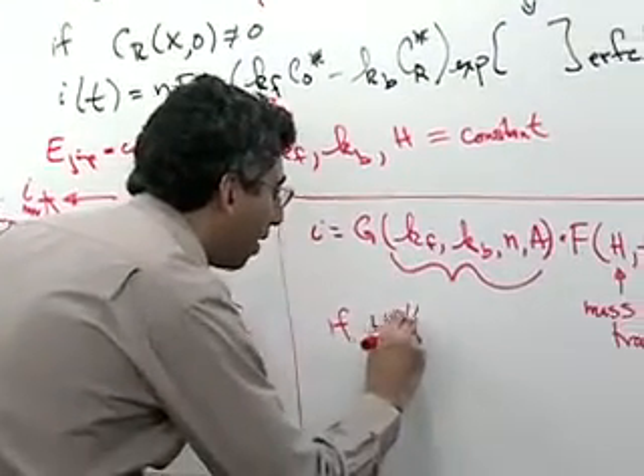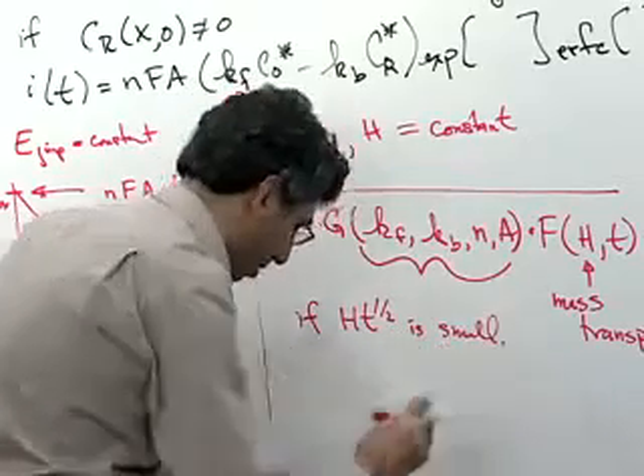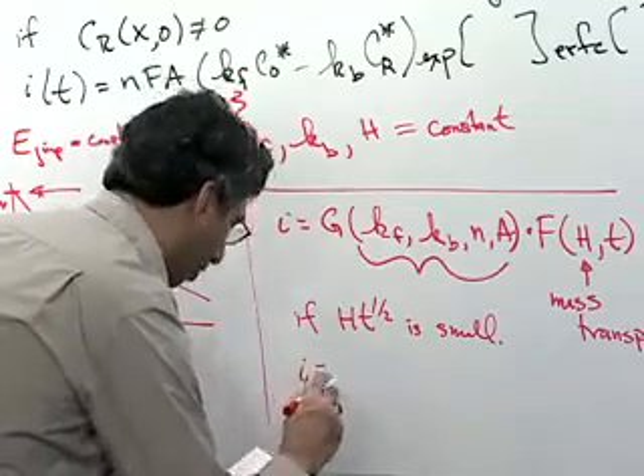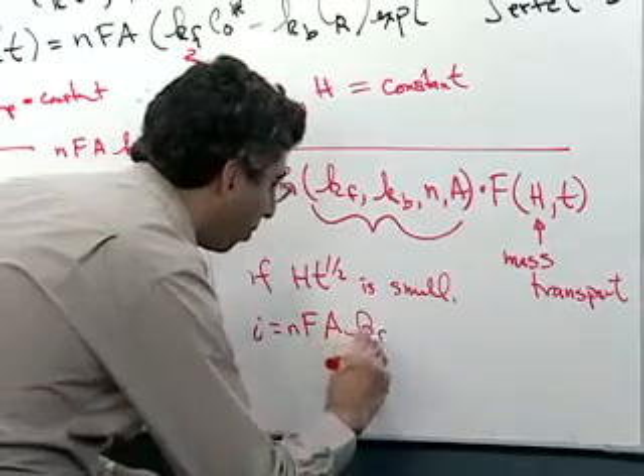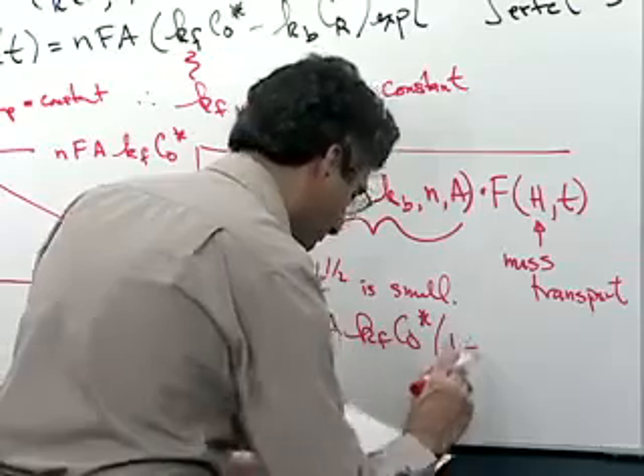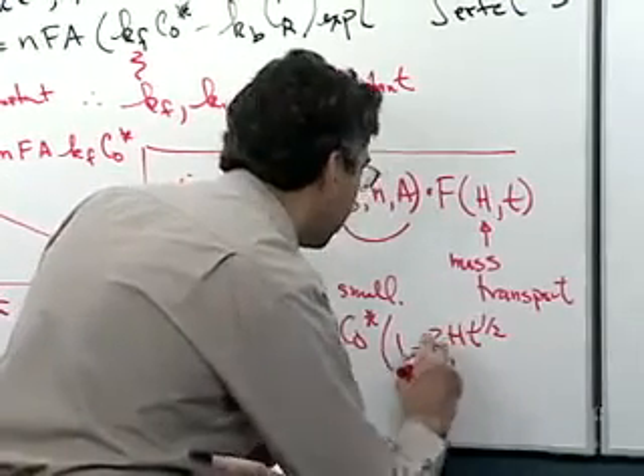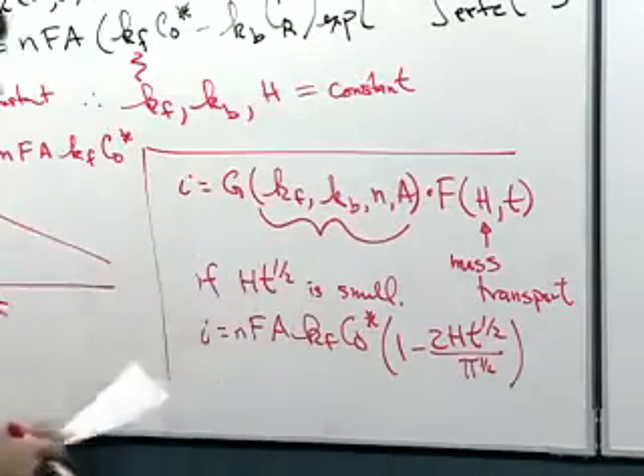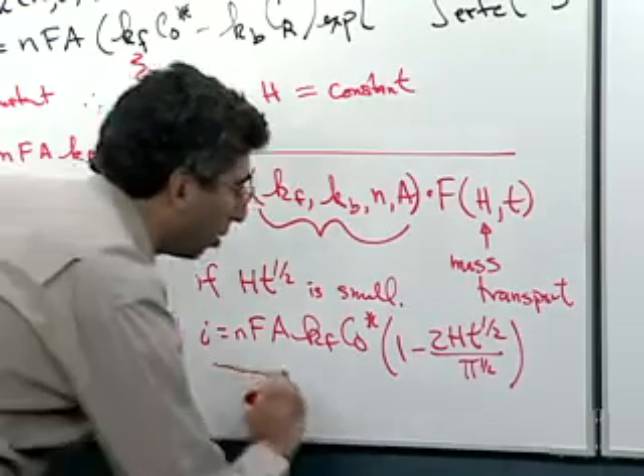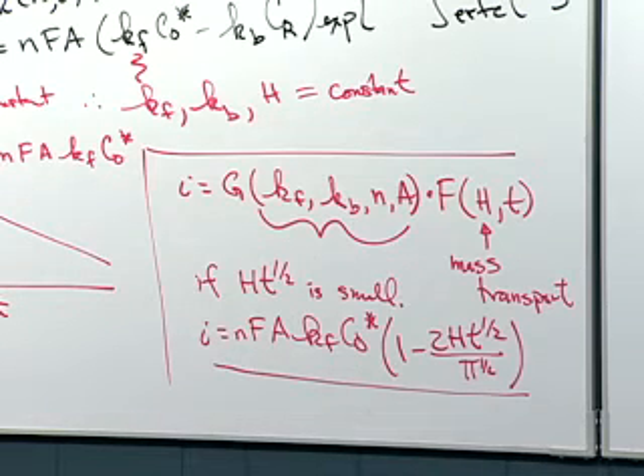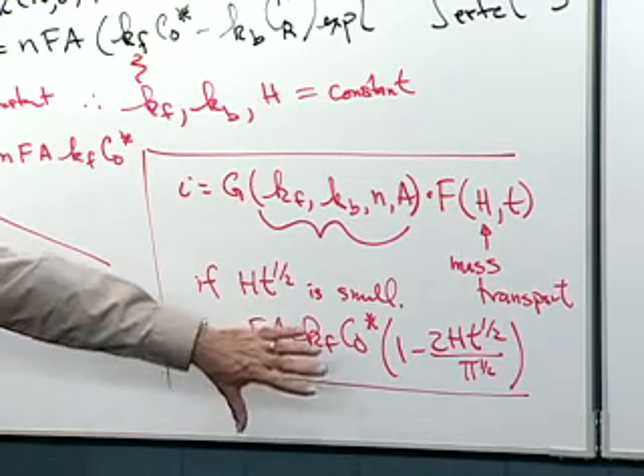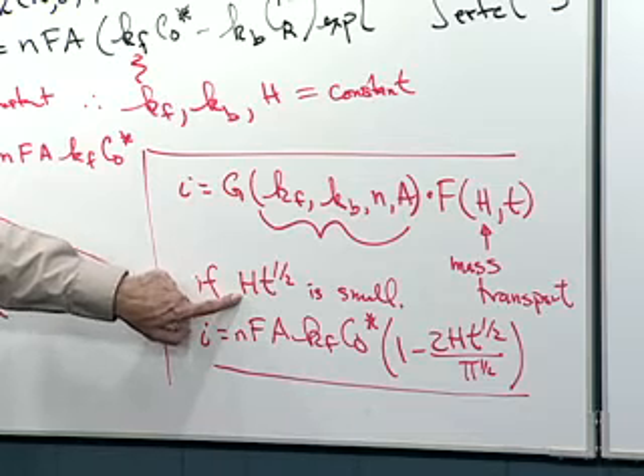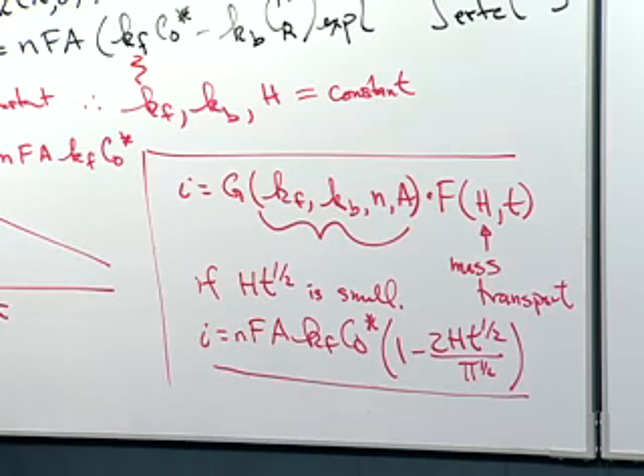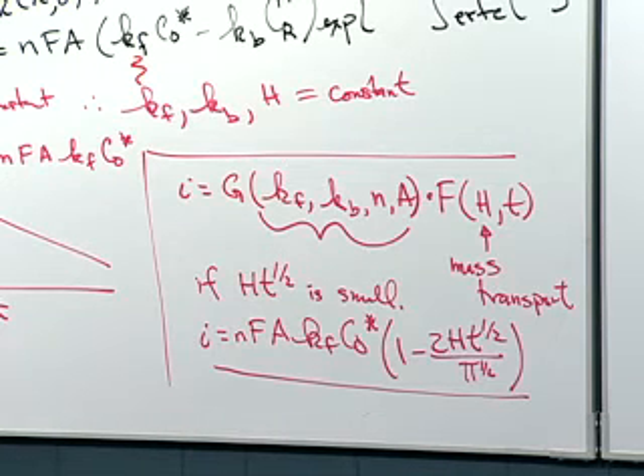And it turns out, if h times t to the 1/2 is small, I can rewrite this as the current is equal to the standard parameters nFA, k forward, bulk concentration, times 1 minus 2 times h t to the 1/2 divided by pi to the 1/2. So a fair amount of math going on here, and we end up with this statement right here. And I can guarantee that this condition is met either by choosing my potential step correctly or my time correctly. And it's the potential step that you're going to want to control, because you don't have that much control over time because of the square root dependence right there, and on top of which you've got to run your experiment over a reasonable amount of time. So by picking the correct potential step, I can get this situation.